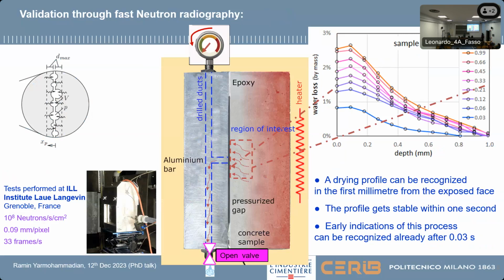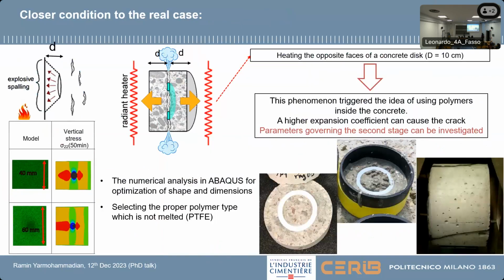In my PhD, we wanted to be more realistic. This time, we didn't want a gap; we wanted a real crack inside the concrete, like what you see here, a crack which is generated at the time we need it. So we started to think about two symmetric concrete covers, heated from two sides and separated by a crack which will be generated at the right time. And this crack, maybe the interesting part, is triggered by a polymer. This polymer has higher thermal dilation, and when you heat it, it expands more than the surrounding concrete. It pushes the concrete next to it, and then we have the crack there, and we can understand whether the crack is going to be unstable or not.